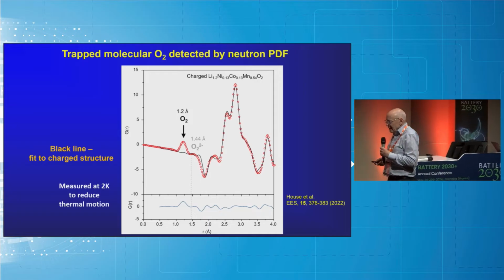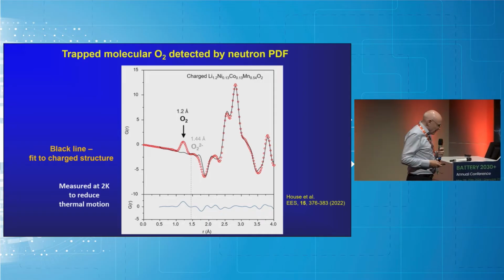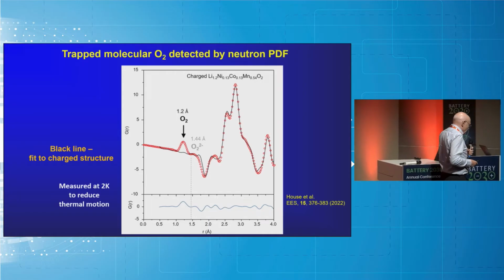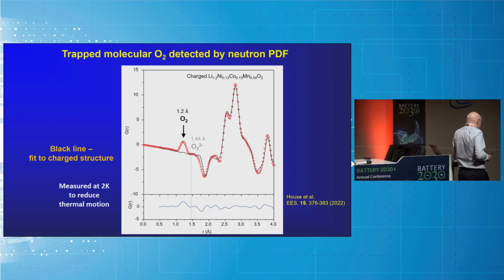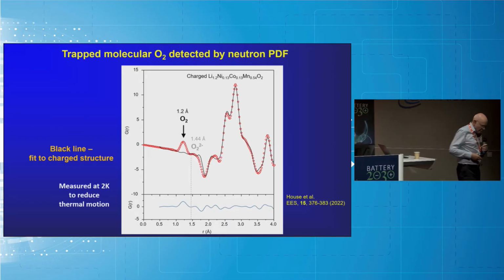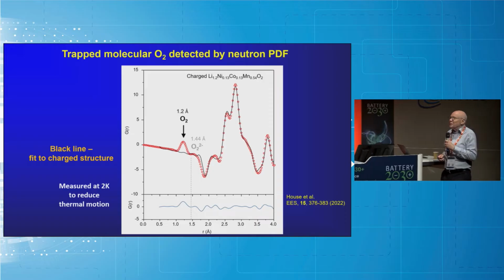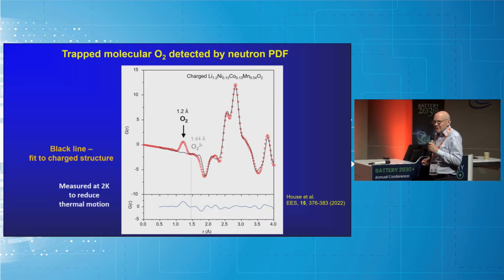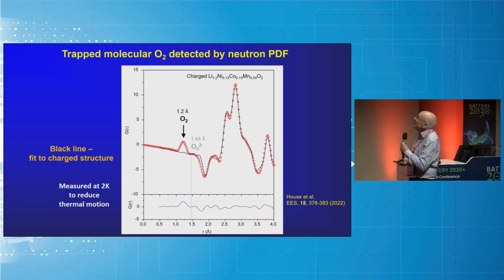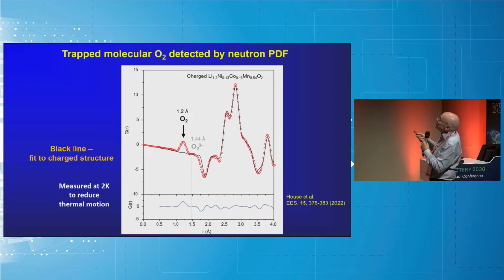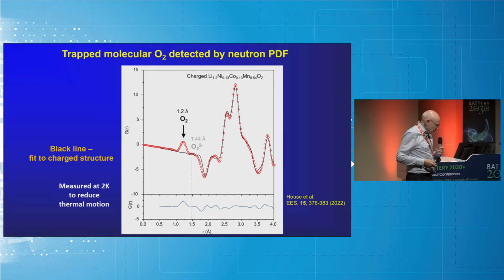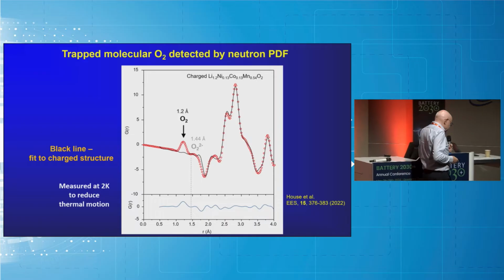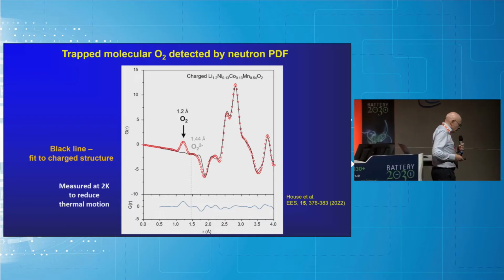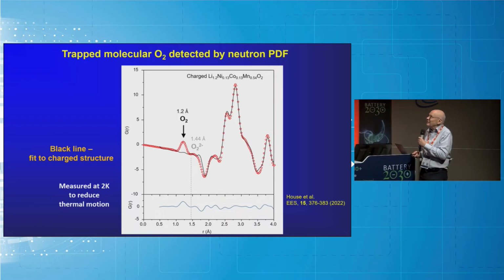So, RIXS is powerful, but it's useful to have other techniques to confirm that what we're seeing in molecular oxygen in these particles is really correct. So I'm going to show you two other pieces of completely independent evidence. The first one is neutron PDF, neutron pair distribution analysis. This is on the charged lithium-rich NMC material again.